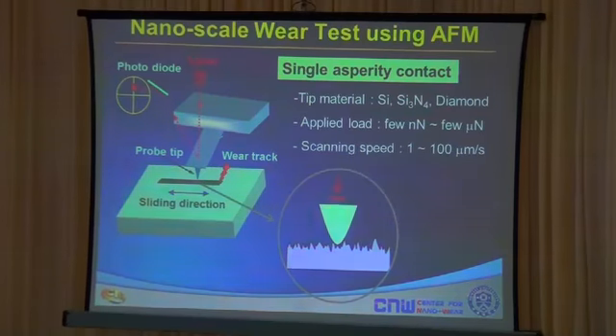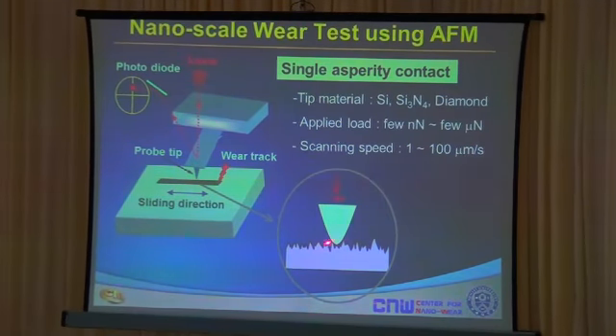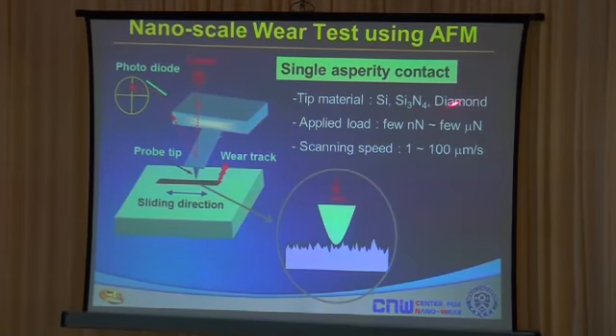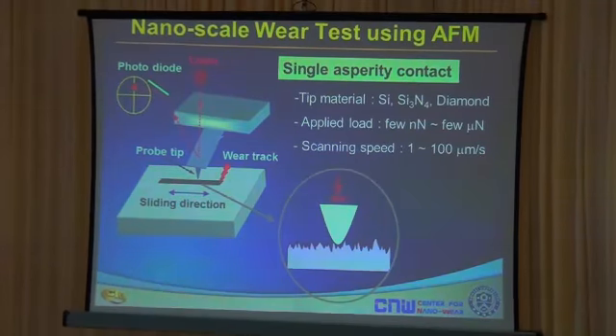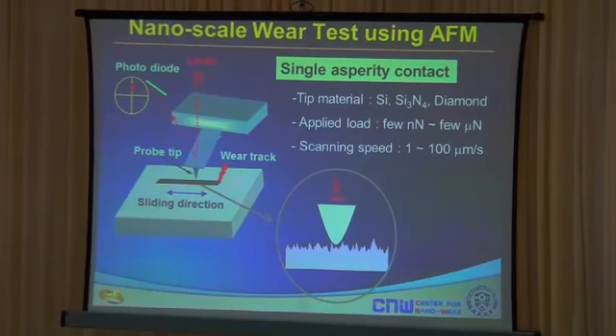But the issue is, because it uses a very sharp tip, there is an issue of wear of the tip as it slides over the surface of your sample. The tip materials that we commercially use are silicon nitride. Sometimes we use diamond, which is much harder. The applied load is in the range of a few nanonewtons to a few micronewtons. The sliding speed is on the order of tens of micrometers per second. This is how we can utilize this amazing equipment to study nano-wear.